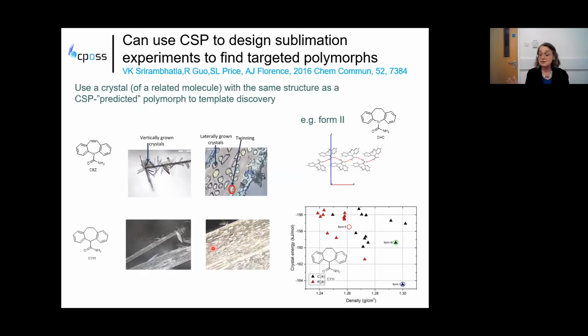We have done other experiments using the crystal structure prediction to actually try and find new polymorphs. So this molecule carbamazepine had 4 polymorphs, but all of them had double hydrogen bonds, and our predictions were pretty clear that it ought to be able to form a hydrogen bonded catemer, as was formed by the closely related molecule dihydrocarbamazepine, form 2. And so the experimental colleagues used crystals of this molecule in the required crystal structure and then sublimed carbamazepine onto them. Some of the molecules just carried on growing, but enough grew out and stuck out that you could take them off. And yes, this was a new polymorph, form 5.